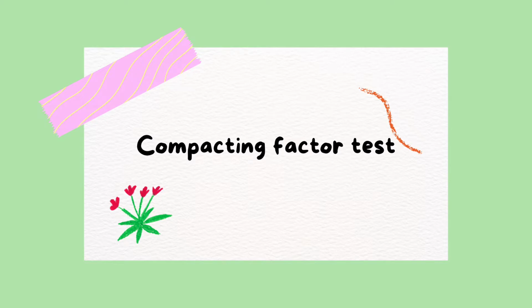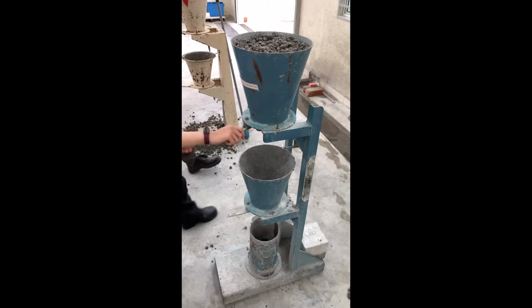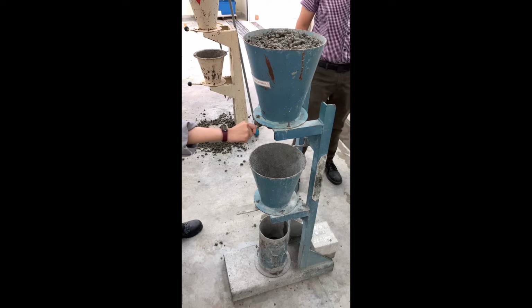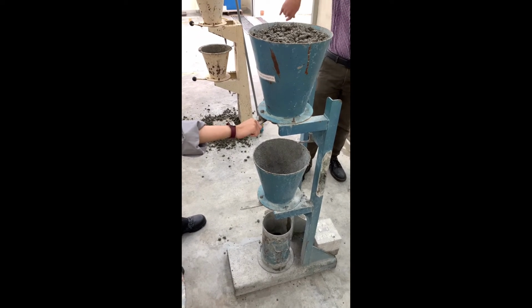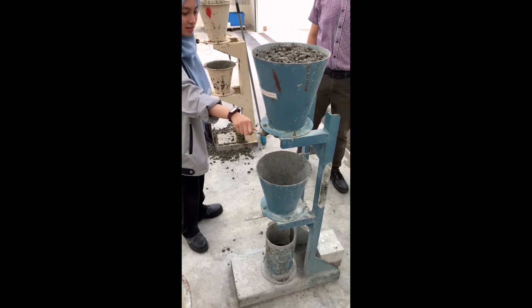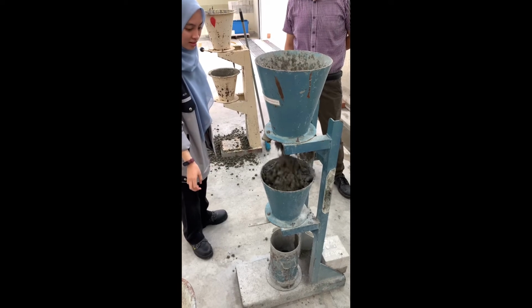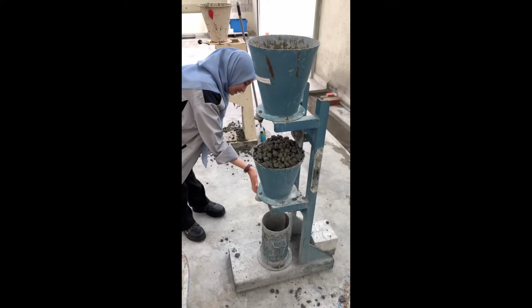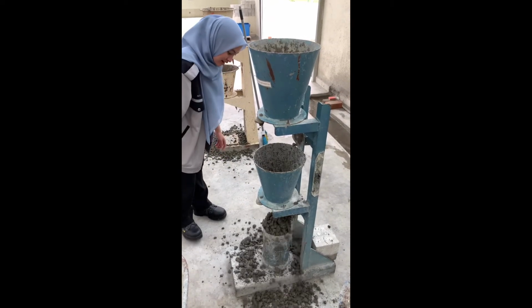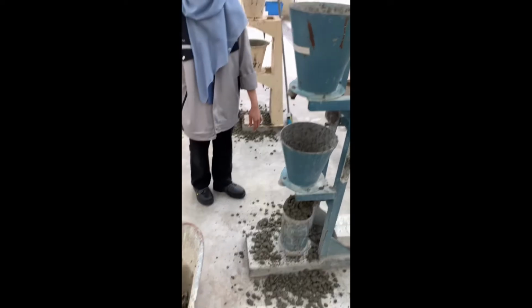Next, the compacting factor test. After pouring the concrete mix into the upper hopper, open the hopper and let the mix fall into the lower hopper. Repeat the process and the weight of the cylinder is measured. Fill the cylinder again and compact it using a tamping rod 25 times. In our case, the compaction factor is 0.98, meaning the workability of our concrete is high.